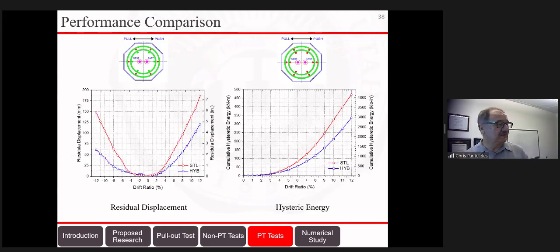Here on the left, you can see the performance comparing the steel, which is the red graph, and the hybrid, which is the blue graph. And you can see at 22 millimeters, which is the 1% that the codes consider reasonable, it's very close. I would say that the hybrid, though, still does better. And on the flip side, when we look at the hysteretic energy, the steel column does better than the hybrid, even in this case where we have the post-tensioning bars.